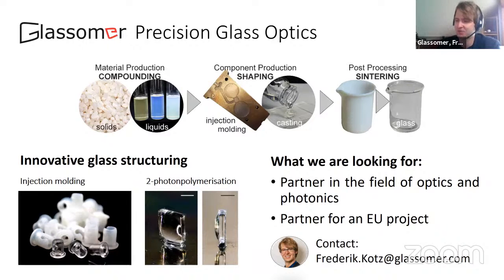On the right side, you, for example, see a 200 on 200 3D micro-optical lens, which we have printed using 2-photon polymerization and then turned into fused silica glass. And this is our latest technology, high throughput injection molding. So in the back, you can basically see the green parts, which we're injection molding with cycle times of a few seconds. So we could make thousands of these within an hour. And then they are basically converted all at once in a batch process to glass within 20 hours.